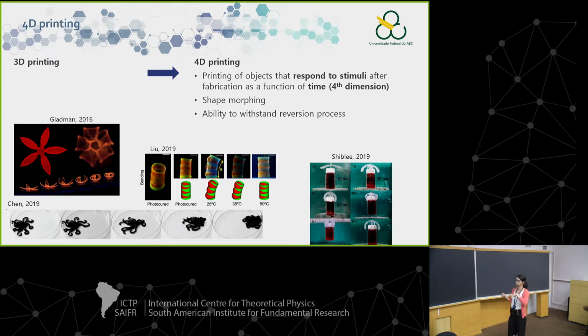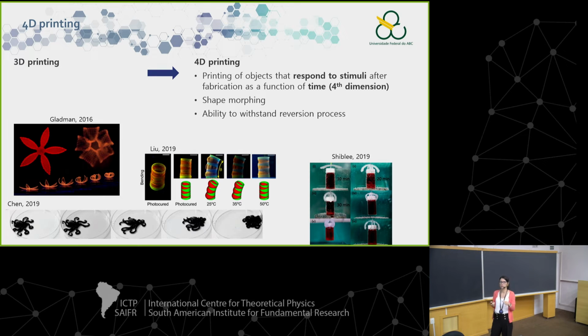Here it is a grip that is pH sensitive. So at high pH, it swells. No, it shrinks, sorry, so it is able to grip this flask. Then it is placed in a tank with a low pH, and so it opens again, and so it's like an actuator. And in that case, this small octopus has been obtained by placing ferromagnetic nanoparticles in the mixture, and by applying an external magnetic field, we can make this octopus move.